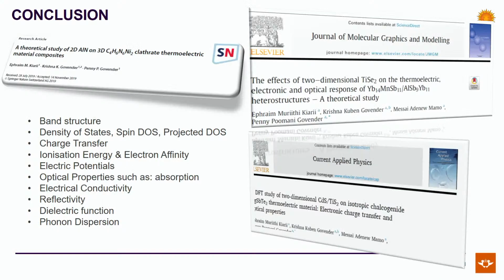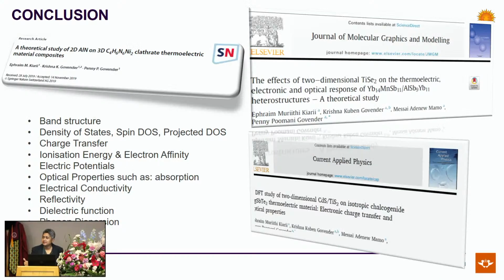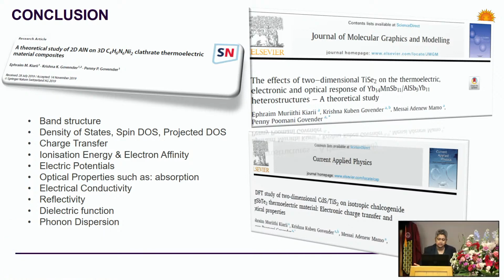So some of the calculations that we ran were quite a bit. If you see on the left-hand side, we did band structure calculations, density of states, spin density of states, projected density of states, charge transfer, ionization energy and electron affinity, electric potentials, optical properties such as absorption, electrical conductivity, reflectivity, dielectric function, and phonon dispersion. As you can see, we also published a range of papers in this area.